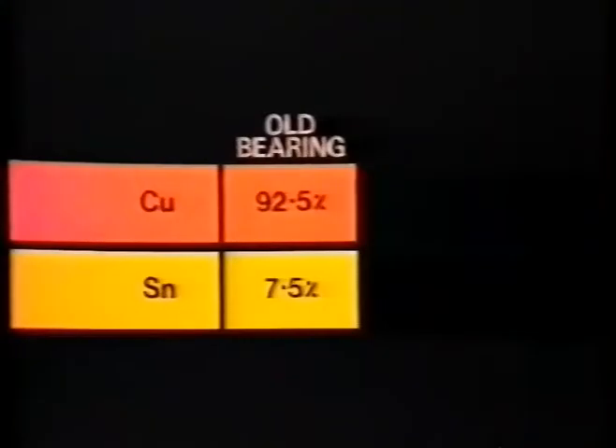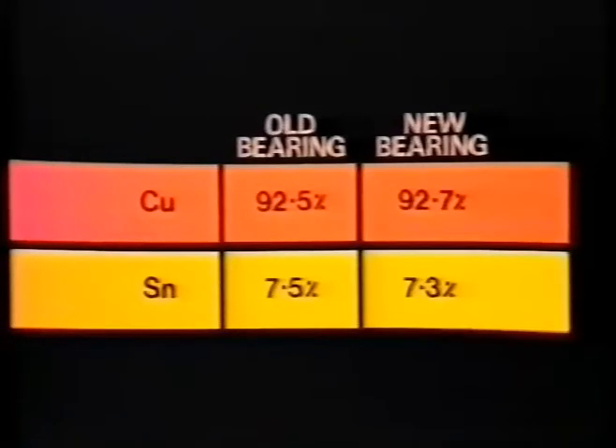Now, the first thing the metallurgist would do would be to check if the chemical composition of the new and the old bearings were the same. And he would do this by taking samples from a variety of locations and sending them off for chemical analysis. These are the results of the chemical analysis. The old bearing contained 92.5% copper and 7.5% tin, and the new bearing contained 92.7% copper and 7.3% tin. So there's no significant difference in the overall chemical analysis of both bearing materials.